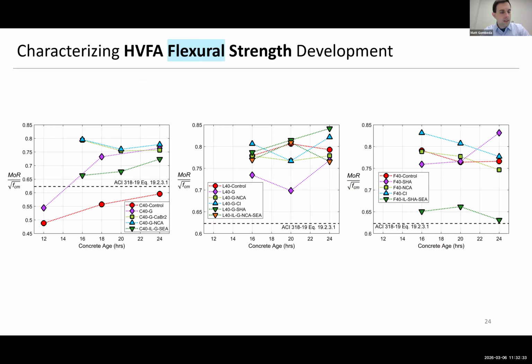Now here's an interesting one. I like this plot because when we relate modulus of rupture, typically it's done by taking the square root of the compressive strength, and the factor in front of it from the ACI code in chapter 19 is usually 7.5. And forgive me here, they're in metric units. The number is 0.62 in metric instead of 7.5, but you can see here we plotted for the different mixes to determine how conservative or unconservative that ACI equation was for 2 reasons, right?